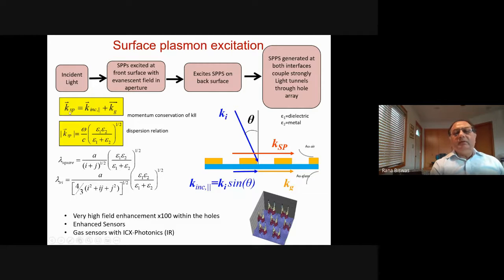The momentum conservation of the parallel component of the wave vector tells you that the surface plasmon wave vector is the incident wave vector, parallel component, plus the reciprocal lattice vector of this periodic structure. And this can be solved quite readily, and it gives you the dispersion relation for surface plasmons, which actually lies slightly below the light line.